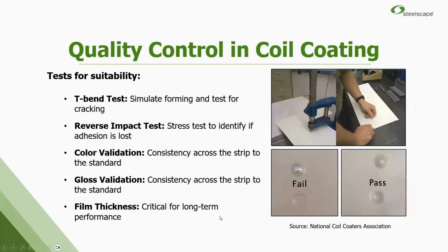The quality control that we do is extensive, and it's to mimic the fabrication that's going to happen downstream. So we bend it, we bump it, we impact it, we scratch it to make sure that this paint is going to hold up. That's from a formability point of view. Color is huge, right? We need these colors that get run over and over and over to look the same visually time after time. So we're controlling color very tightly, both with computers, also visual assessments. The gloss needs to be consistent and the same from run to run, coil to coil. And the film thickness, as tiny as that film thickness is, we have to control it very tightly because it is key to the long-term performance and the warranty performance that these products are going to have.